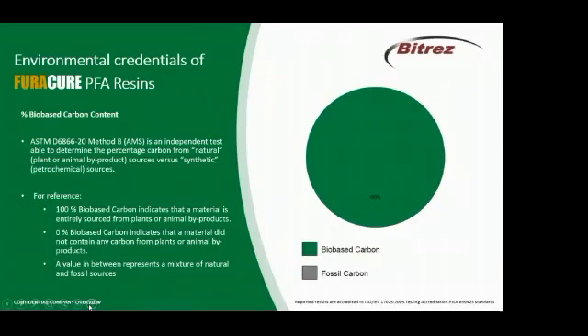And what you can see here is a screen grab from a third-party independent testing laboratory, which is running a test, ASTM D6866-20, which is a way of determining the bio-based carbon content of a material when compared to the fossil-derived carbon content. And as you can see here, the PFA resins are 100% bio-based, which obviously is certainly good in relation to our work around the 12 principles of green chemistry.